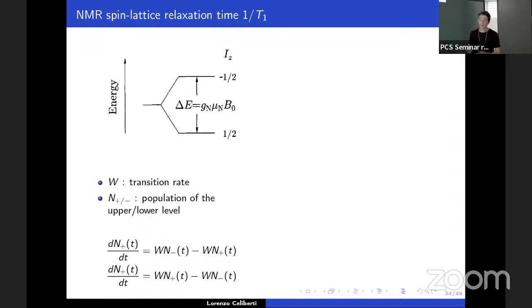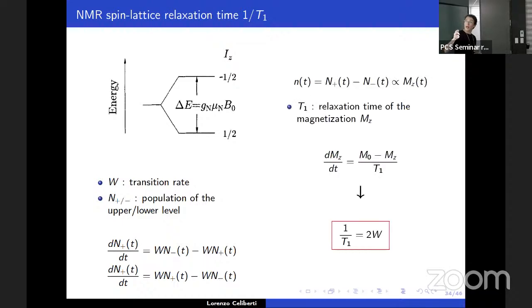At the microscopic level, for example, your nucleus is spin 1/2. You have a splitting due to the Zeeman field, or the static field, and you basically have transitions between these two levels, characterized by a transition rate W. If you define the populations of the upper and the lower level, plus and minus, very intuitively one can derive this kind of master equation. By defining the population difference, which is proportional to magnetization, you can relate your relaxation time to the microscopic process. So the relaxation rate 1/T1 is proportional to the transition rate between the nuclear levels.